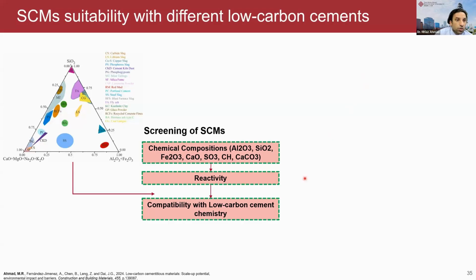So to do that, I also did some screening, such as to study the chemical composition of these materials. If you see this ternary diagram, I have shown the chemical composition of these materials. From the literature, I gathered more than 100 articles. I tried to see what their reactivity is, and then I tried to check the compatibility of these supplementary materials with the different low carbon binders.